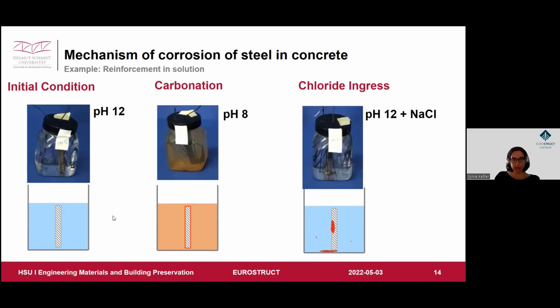As soon as we have corrosion, we have a flow of electrons, which you can easily measure as a current. Sure, if we do not have any corrosion at all, we won't have any current. Now for the carbonation, here we measured the current as well, and we ended up with 0.36 milliampere. Now you can think, do we really need to be concerned about a corrosion current of about 0.36 milliampere? Especially since it's just a current, normally we have to calibrate it against the area, in order to have a corrosion current density. Is it really a lot? Is it not? What does it really mean if the structure still has to serve for 30 or 50 more years?